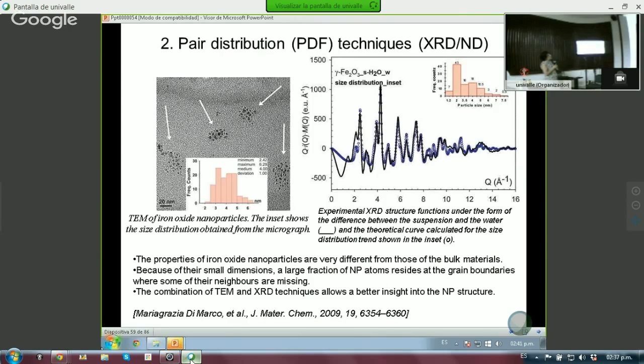Now the pair distribution technique, this is, again, something you can do combining both X-rays and neutron diffraction because they see it in different ways. And what is interesting is, in this case, this is the experimental X-ray diffraction structure functions. And you can see the differences in the distribution between the black curve and the experimental data, where one is calculated and the other one is measured.